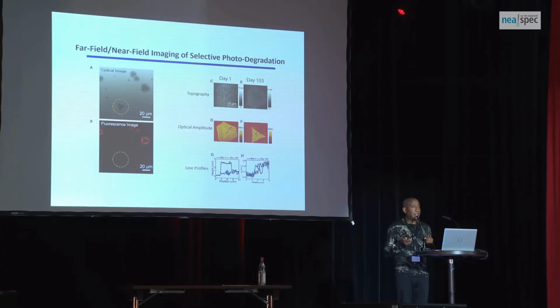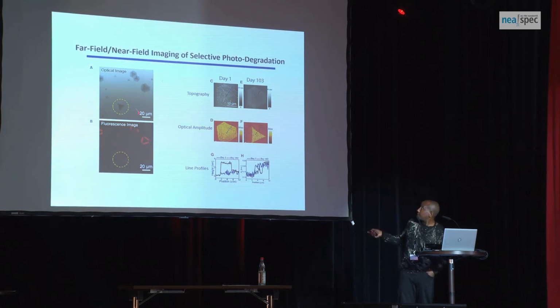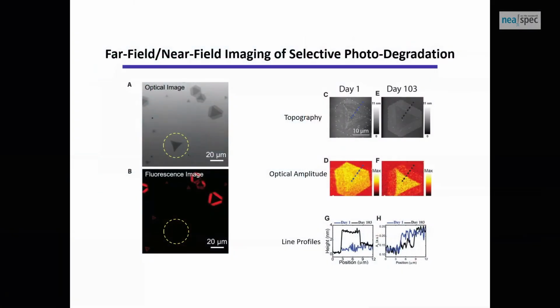to use correlative imaging: near field with tip-enhanced PL, tip-enhanced Raman, as well as optical imaging and AFM, all in one, right? That's nice. If you look at it with an optical microscope, the sample that we did the experiment on is circled there. If you compare this sample with the one that we did not look at, given the same ambient condition, the whole flake is exposed to the same condition for many days. But the difference that you see between this and that, even just with optical microscope, comes from the fact that that particular sample is exposed to laser.